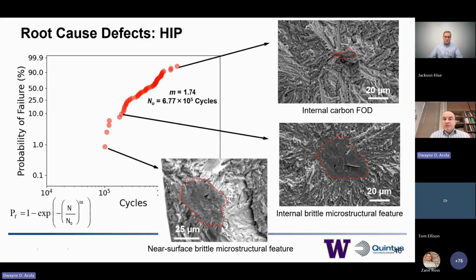So the purpose of doing this is to make sure I point out, one, we get an increase, of course, in the Weibull modulus, but more importantly, throughout the fatigue life distribution, we don't see any contribution of voids to fatigue failure. It's all something that has become evident as a result of the fact that now all the void type factors are repaired.